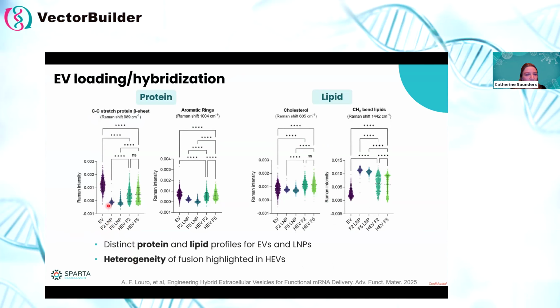If I take just this left-hand graph, you'll see there's quite a big spread of protein in the EVs, this protein signal. This is what we expect because these are cell-derived biological nanoparticles, so there's a lot of inherent heterogeneity. Then these next two conditions, the second and third, are two different types of LNP, and as we'd expect, there's very little protein signal here. What's very interesting is that when combining these LNPs and EVs into the hybrids, there's a lot of heterogeneity in both of these conditions. This shows that in the final formulation, you probably have some particles which are still EV and still pure LNP, as well as quite a broad, heterogeneous spread of these hybrids.